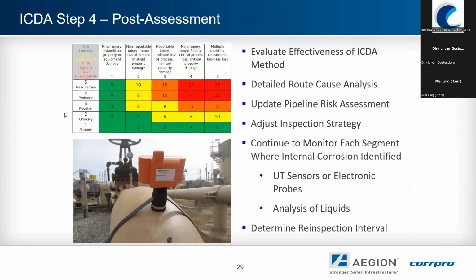The post-assessment phase, then, we have to look at the overall effectiveness and demonstrate that it really worked. If there was any corrosion identified, complete a root cause analysis to understand what was causing the problem. Update the risk assessment. This is a requirement as well. A standard format is shown on the top left there in a risk box. If there are any complications or blind spots found in the technique, it's necessary to change the inspection strategy.